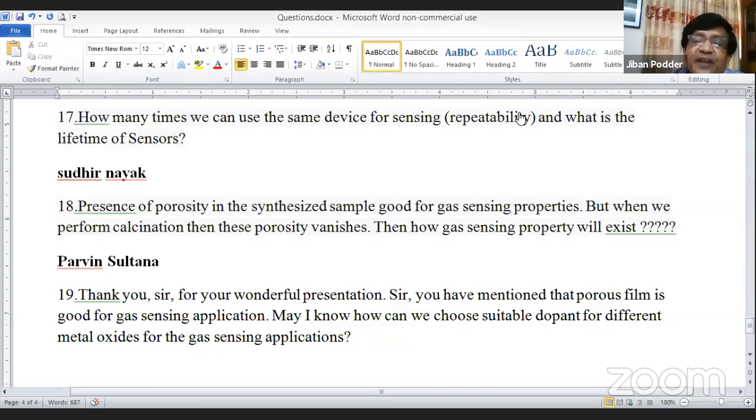So the selection of this material is better by choosing the same ionic size as the prime material first of all, and it should be equal or a little bit less, which is normally better for selecting the dopant element, so they can interact with the interstitial site or substitutional site, or they can play an important role within the matrix mother material. That is the phenomenon we are searching. We don't know everything, but we are searching. So research is the searching of new material from the known material.